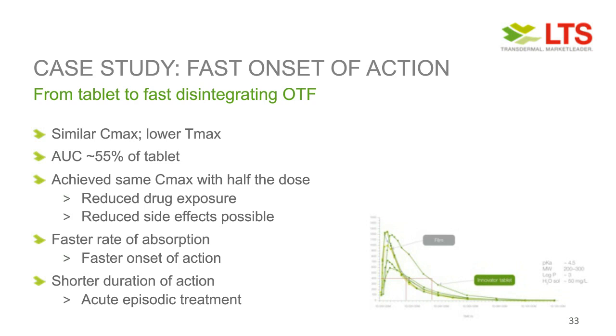But at the same time, the AUC of the tablet was lower to achieve the same Cmax, down to 55%. And this was also done because we had half the dose of the API. So with the same API at half the dose, we were able to reduce the drug exposure and therefore possibly also the side effects which come along with this higher dosing. We achieved a faster rate of absorption and therefore a faster onset of action. And this was, especially in this indication, very important to get a short duration of action. So it's really for an episodic treatment, so fast in, fast out, to avoid potential side effects there.